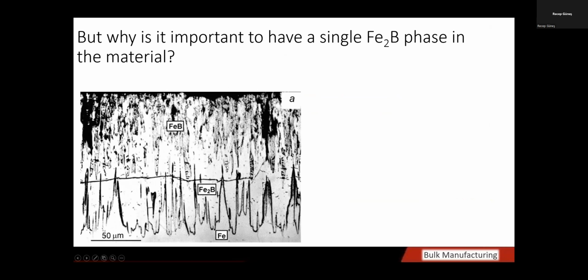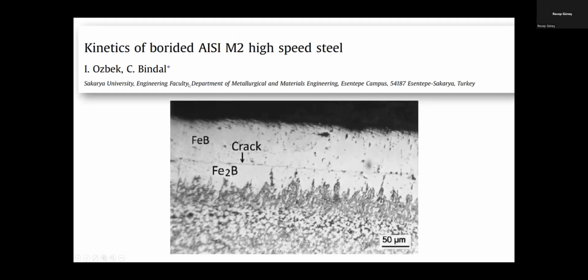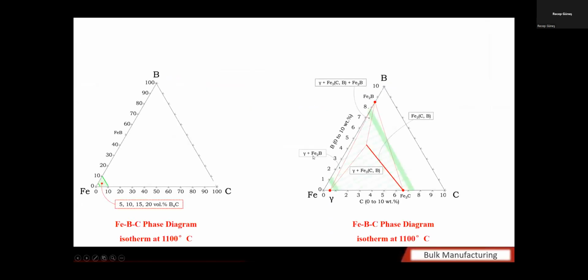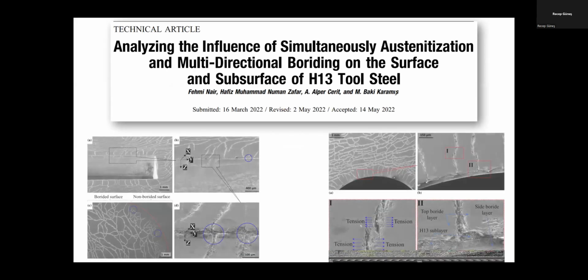So people who work with iron boriding of materials always prefer to form the less brittle, hard and tough, low iron boride phase instead of FeB. Here is another example. A Turkish researcher who studied this also reported cracks being formed on the FeB and Fe2B phases. That is the reason we must ensure that we expect only the desired iron boride phases with the ratios we are using. That also explains the powder mixture ratios we have used, 5 to 20%.